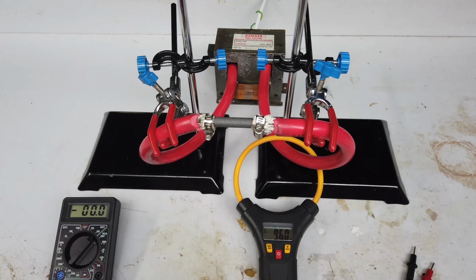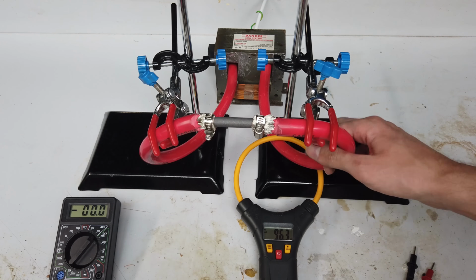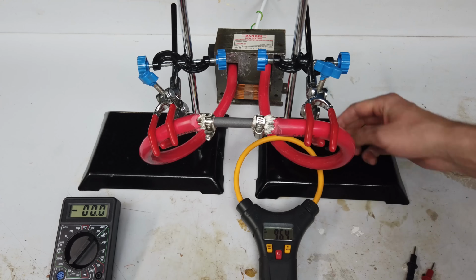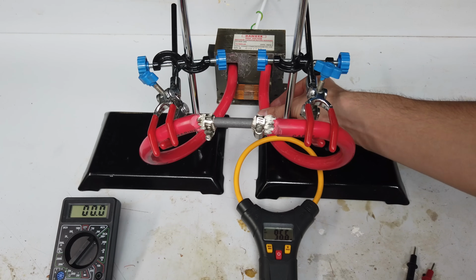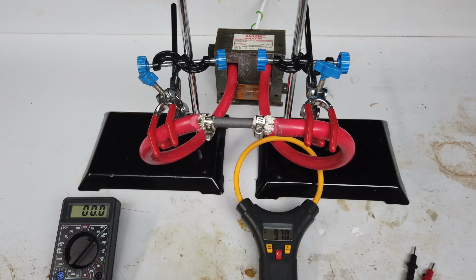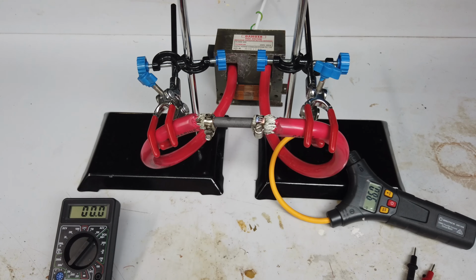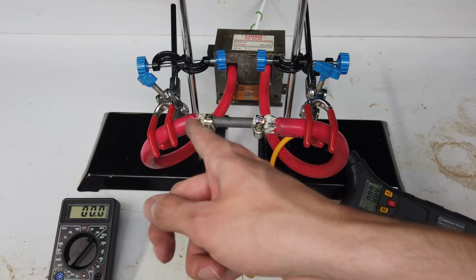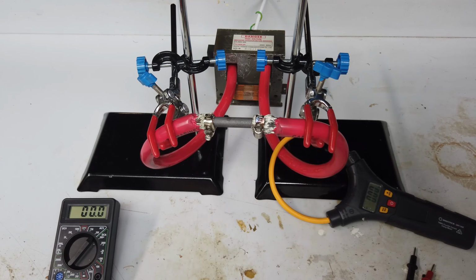Now, trouble is, I don't have a thermal camera, so I can't really tell exactly how hot it's getting. It's obviously not getting red hot, which would be nice. If I touch this wire, this wire's getting... Nah, not really getting warm. So I assume we've got nearly 60 watts of power just directly heating that graphite. Okay, well, 100 amps, but still not hot enough to melt any significant amount of metal. I can also see the insulation of that wire is melting just a little bit, which I'm not particularly happy about. So, good thing that we've stopped it here.